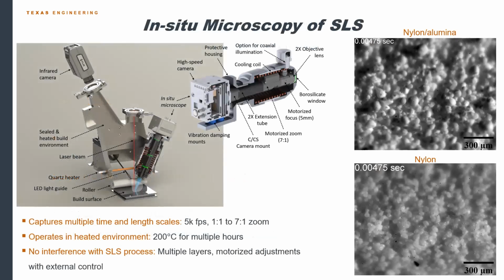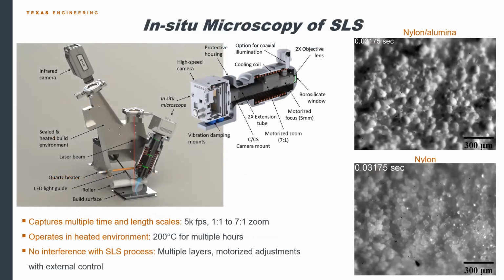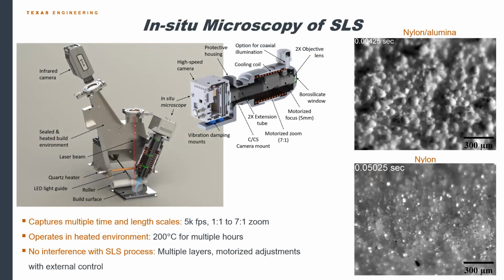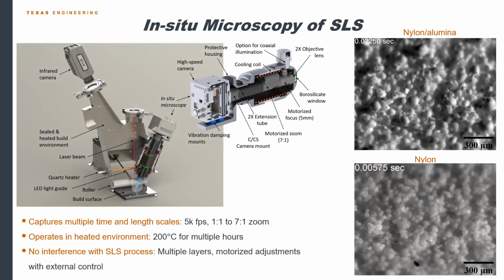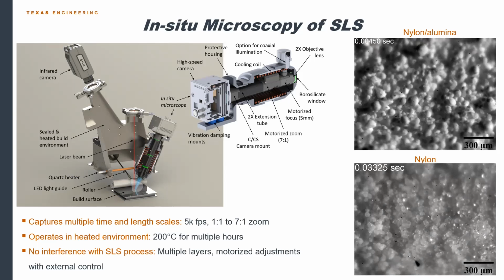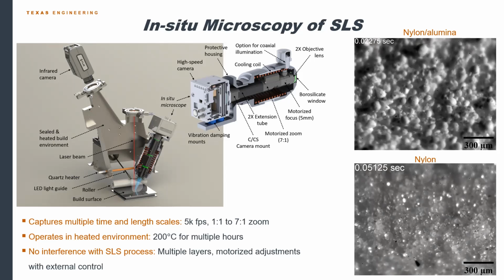So I'll start with indirect selective laser sintering. And I'm just going to give a highlight of a new capability in our lab, which is an in situ microscope for the SLS process. So we went into this work with ceramics thinking that the mixed powder, again, it's mixed ceramic and polymer, behaved very similarly to nylon during the laser sintering process. So we designed this instrument and we actually proved ourselves wrong.